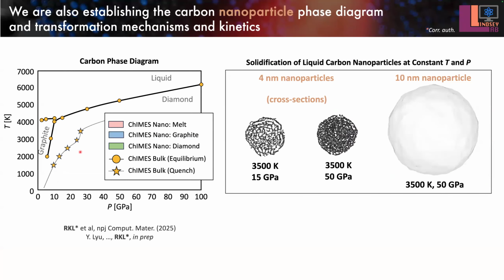So how we're dealing with this is we are taking liquid carbon particles, we put them in a bath of argon. We can use that argon bath to squeeze the system to some target pressure, and then we can cook the particles at a target temperature.